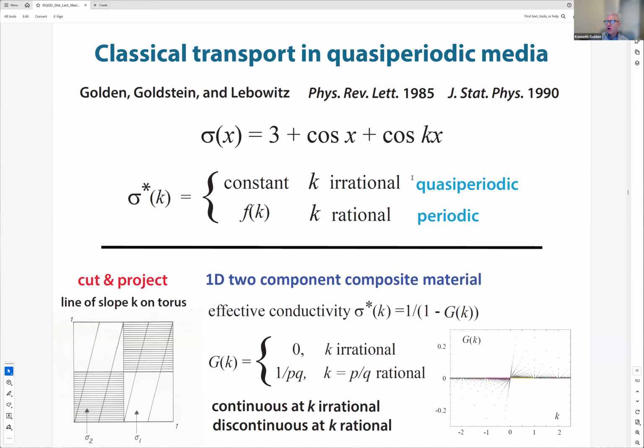And then as I went further with Joel and Shelley Goldstein, we developed what is now called cut and project, where we constructed a 1D quasi-periodic system by taking a 2D checkerboard and passing lines through it. But you can then take a 3D checkerboard and pass a plane through it. It turns out for the 1D case, we can calculate it exactly. And then the graph of the homogenized parameter as a function of k has all this fascinating structure that, to be honest, we have yet to really delve into. I think it will be a great undergraduate project, actually.